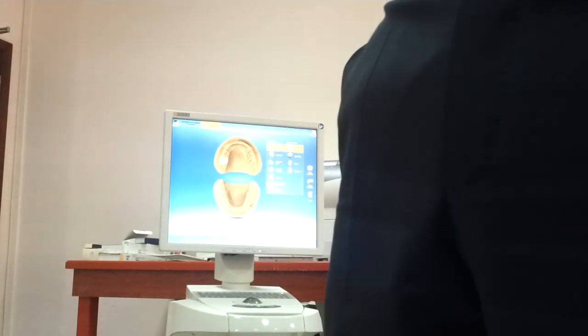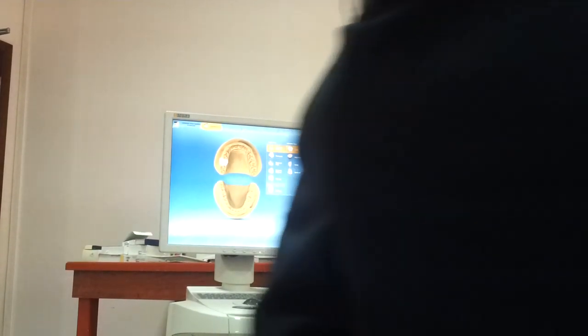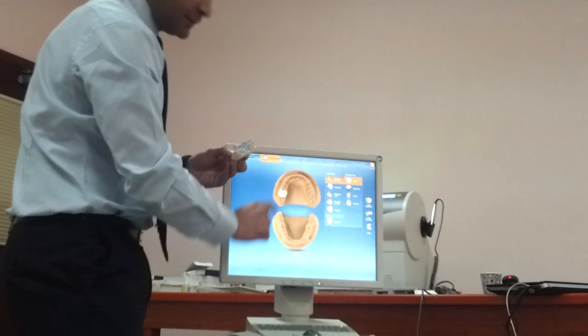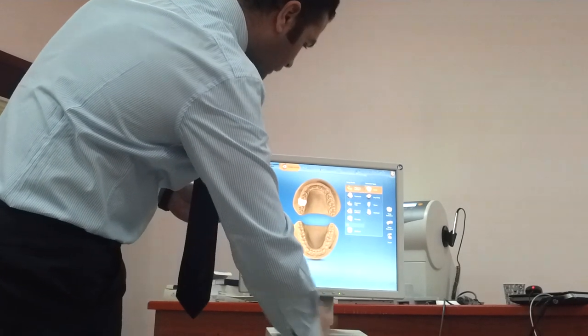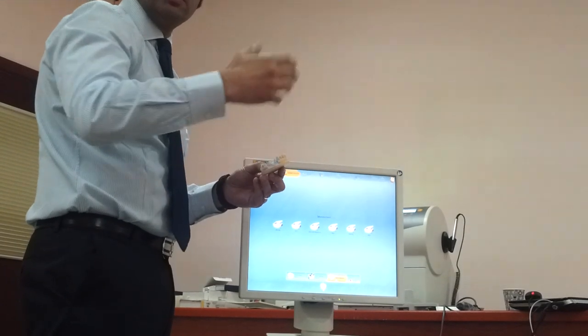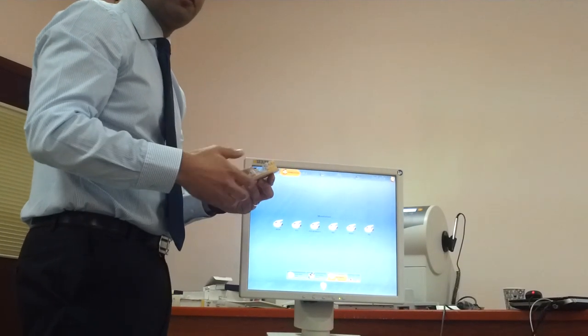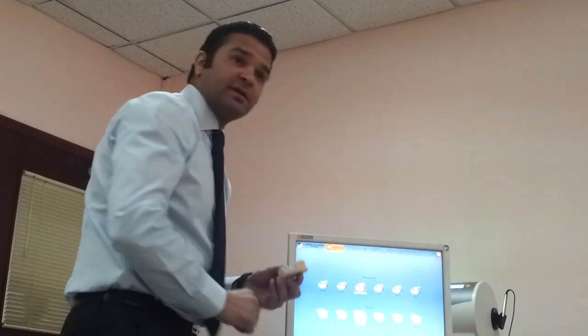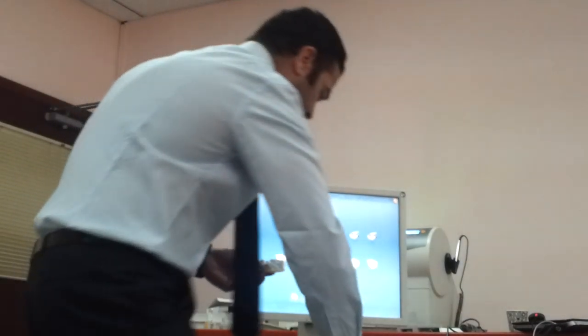My prep here is tooth number 1-6. I have a model with two preps: one for a three-unit bridge on the left side and one crown on the right side for tooth 1-6. I'll choose a crown for tooth 1-6, and the software asks which material to select. For this posterior crown, we need a stronger restoration — lithium disilicate with a flexural strength of 360 megapascal, commercially known as IPS Emax CAD from manufacturer Ivoclar Vivadent.